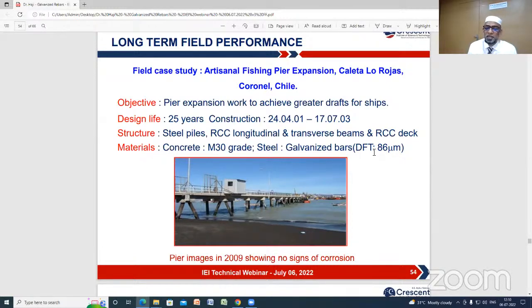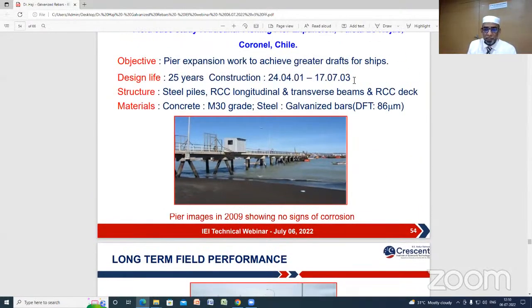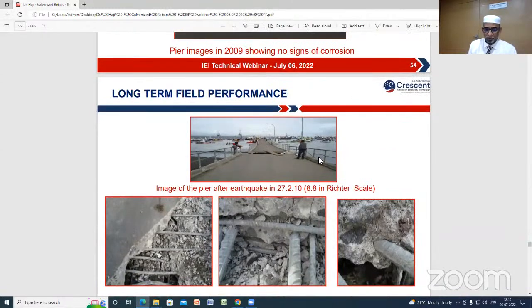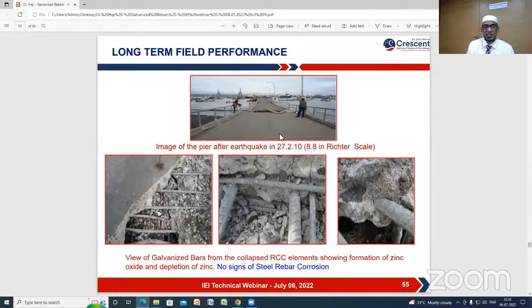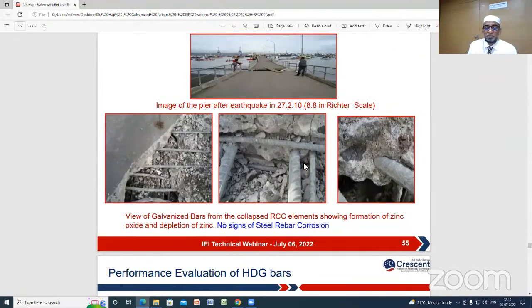Here they used galvanized steel rebars with a coating thickness of 86 microns. The zinc coating was done at 86 micron thickness. It was completed in the year 2003. In 2010, this bridge suffered a severe earthquake, and the bridge was distressed and failed. When they observed the condition of the galvanized rebar, even after 7 years of exposure in severe marine atmospheric conditions, they did not find any corrosion of steel in the rebars. Only zinc corrosion products were observed. This is also a real example of site performance of galvanized rebars. Even 7 years after construction, in marine conditions, it is doing well.